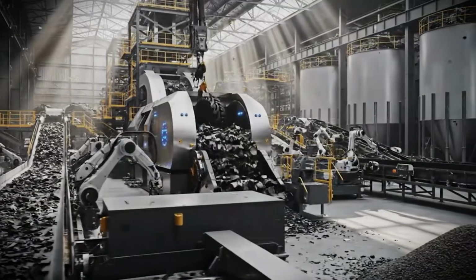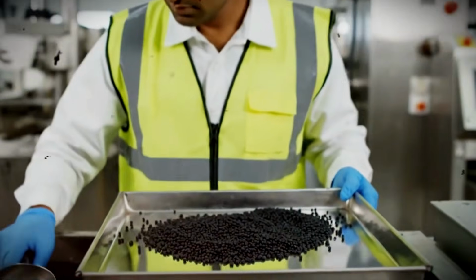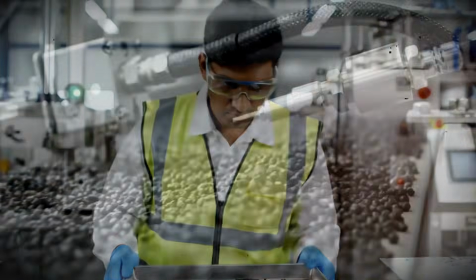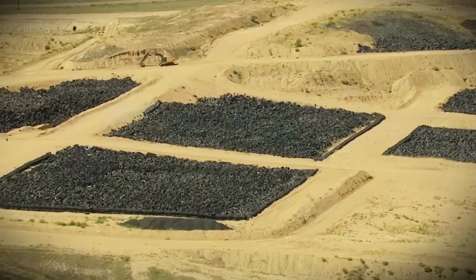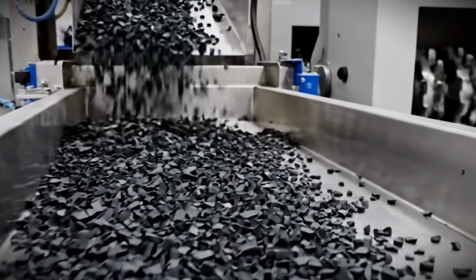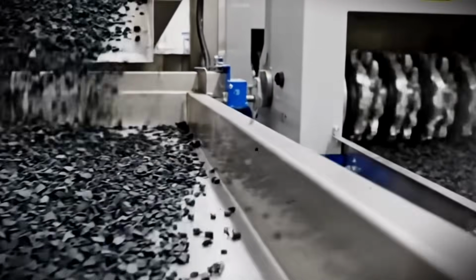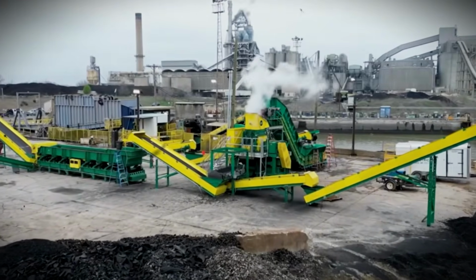The rubber makes the pavement more flexible, so it handles temperature swings better. In Phoenix, where summer pavement temperatures hit 160 degrees Fahrenheit, regular asphalt cracks and develops ruts. Rubberized asphalt stays flexible and resists deformation.